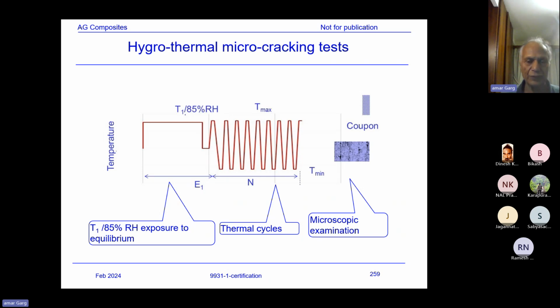During thermocycling, you will be taking the coupons after certain intervals, like 200 hours or 500 hours or 1,000 hours, and try to examine the microcracking by sectioning them and using a microscope examination of the coupons. And then you will assess it. If there are one or two cracks after 2,000 hours or 1,500 hours, you might accept. But if there is a significant amount of microcracking, you will reject the material and look for another material which doesn't develop microcracks. This is an important issue for composites.